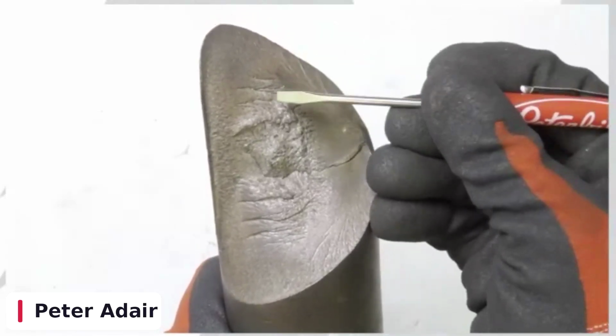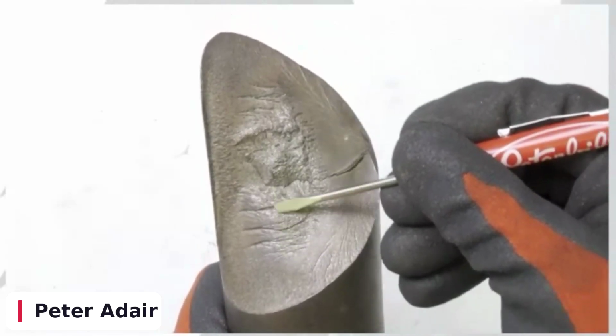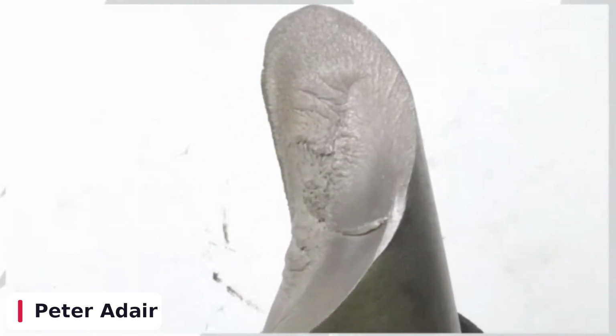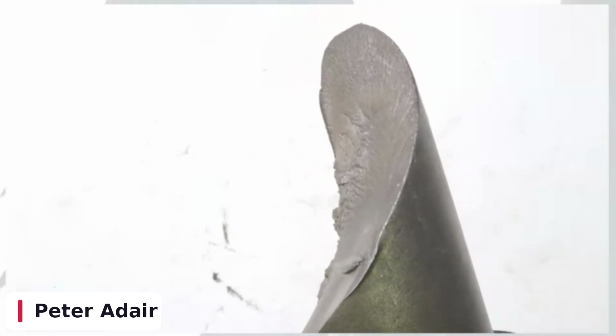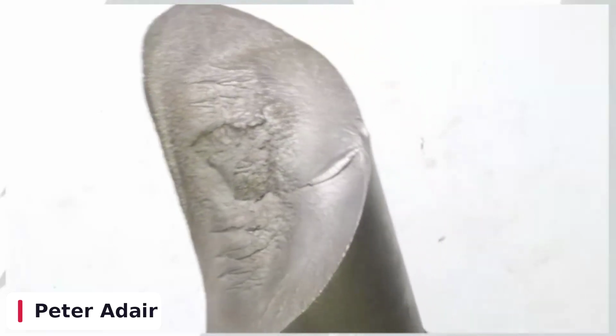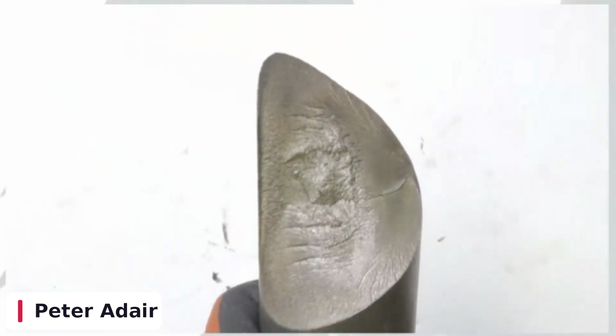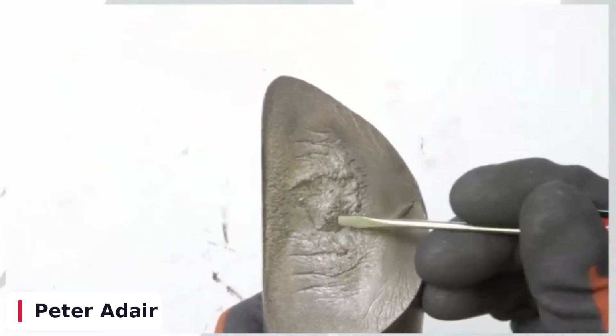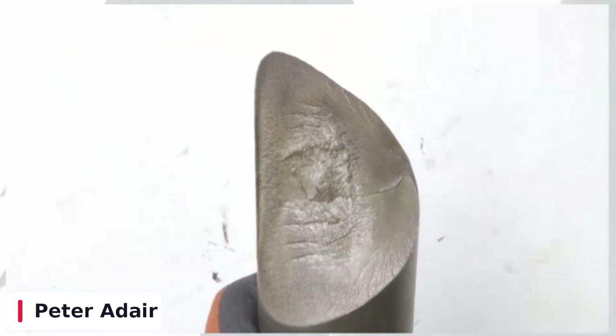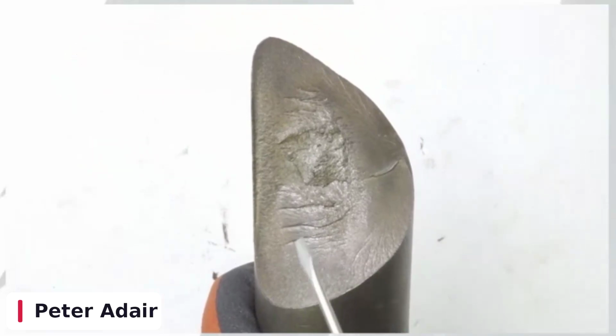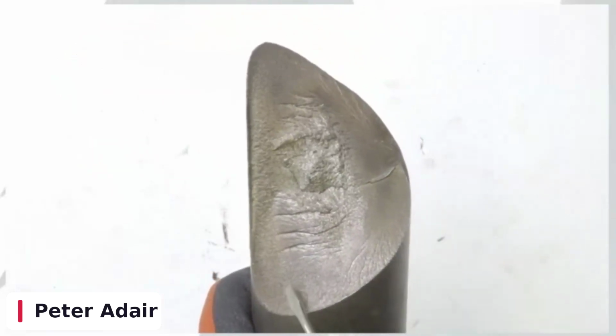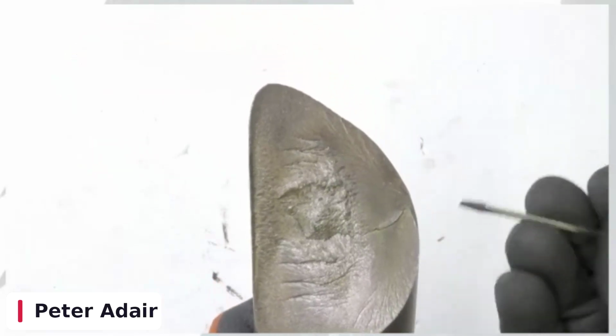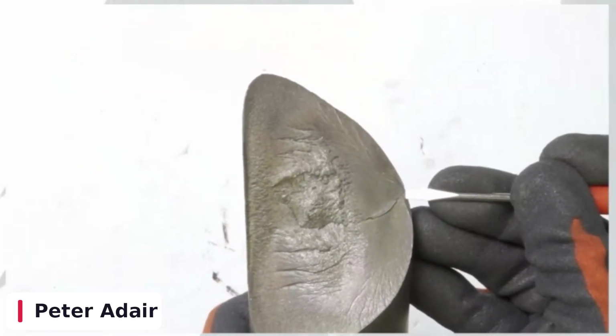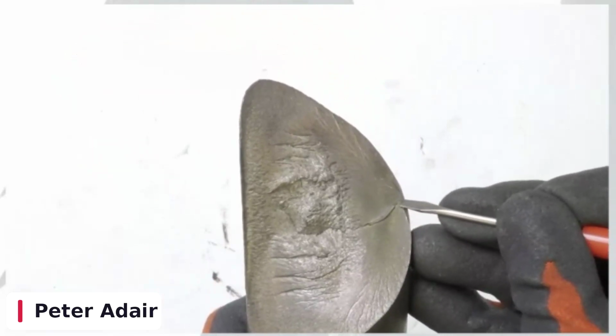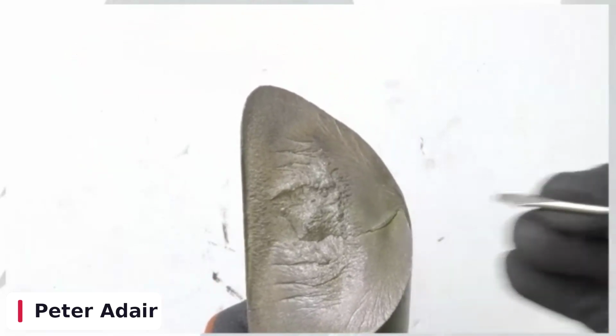The other thing we're going to look at is these guys here. All these striations that are in the steel, these what we call mountain peaks. You guys can see them sticking up there. These mountain peaks, they're called chevrons. Chevrons and mountain peaks will always point back to the original start of the break. So if I look at where my chevrons go and where my grain structure goes back to, everything points to this location right here. This is called a ratchet mark or an origin. This is exactly where our break started. This is exactly the reason this happened.